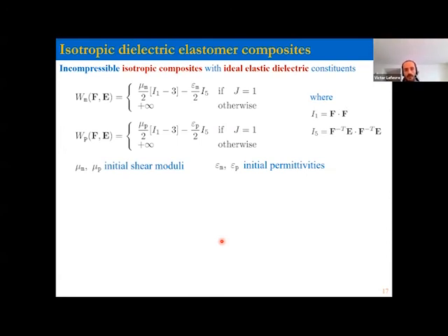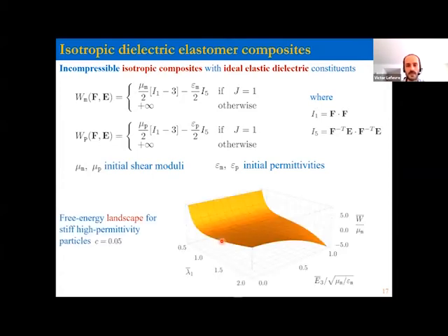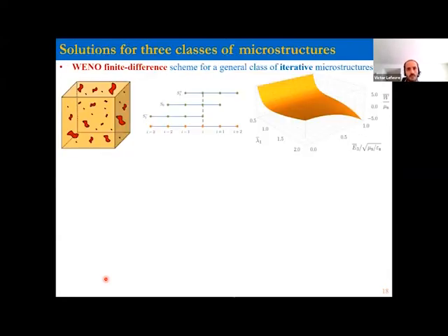All right, so now that we have confidence in the scheme, we use that for the problem where there's no analytical solution. So the response of these isotropic dielectric elastomer composites. And that's what the energy landscape looks like. Again, you follow one loading path or another, and you get the response that you're interested in. All right, so that's results for this first class of microstructures, these iterative microstructures.